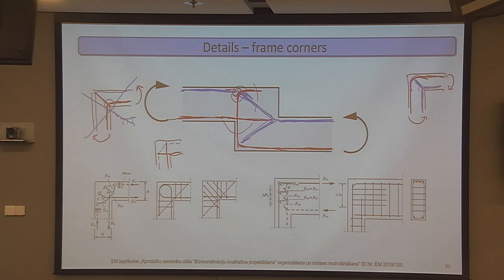The same way for that in here, we shouldn't put it straight on to here, even if the heights happen to match, because we would anchor it to the compression strut, and in a compression strut we would have a tendency for transverse expansion anyway. And then if we put a rebar in it that is anchored, the anchorage is mostly by the ridges of the bar. This will cause also lateral expansion. So it's not efficient anchorage to just let it go straight here. So we should either turn it up or down.